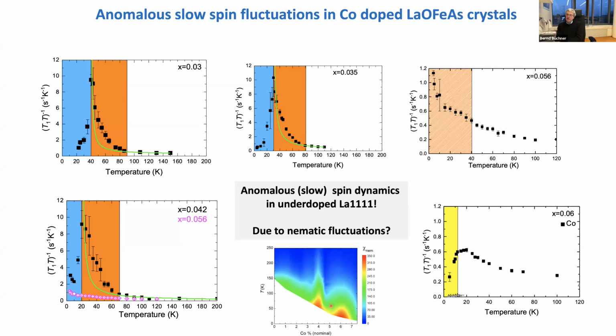We have very soft nematic fluctuations, a very soft lattice, a very soft orbital degree of freedom, and an extremely soft spin degree of freedom. All of that is strongly coupled to electron transport, and therefore it's apparent that you have extremely strong scattering of the electrons. This explains, at least qualitatively, that you are very close to localization. Only if you go to very high doping do these things disappear and things more and more become like usual metals.